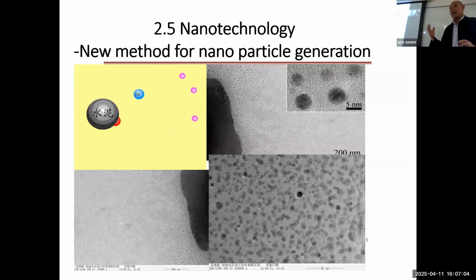And then we found the cement particle can release the calcium ion, just like we discussed earlier. And finally, they can form very small calcium hydroxide. How big? 5 nanometers, and very uniformly distributed in the solution. Very good. And we tried this on magnesium, and we also found we can get a similar phenomenon. We can get about 2 to 3 nanometer particles from magnesium. So we said this is a reliable method. We can use this method to produce nanoparticles using common cement particles. And this is very cheap and a very simple operation.